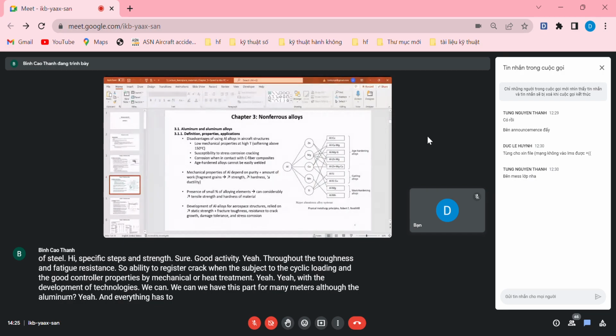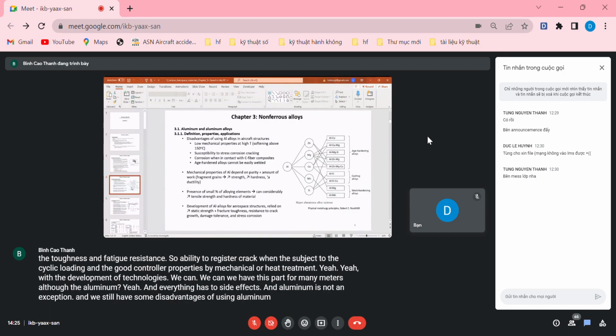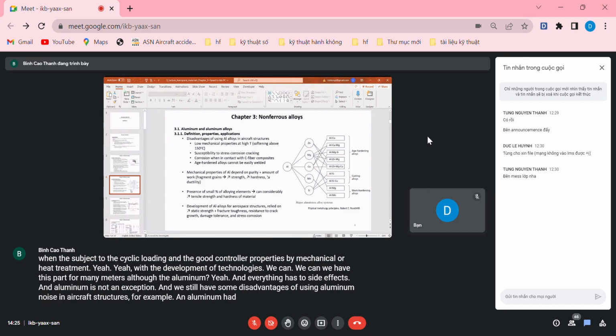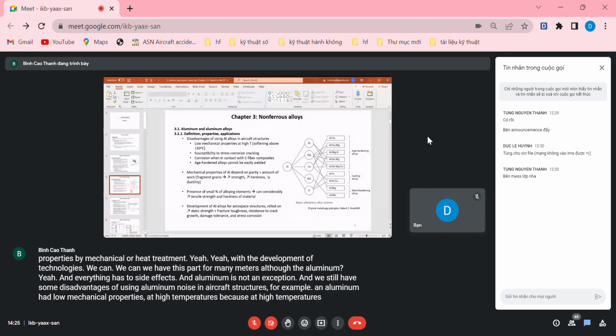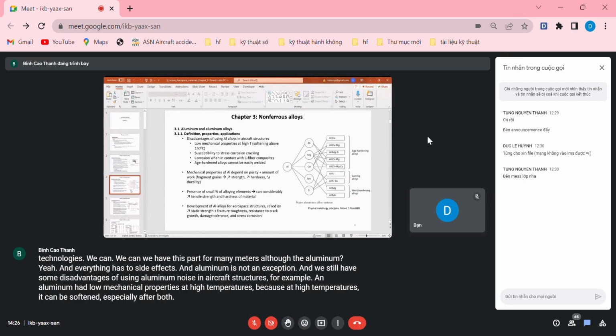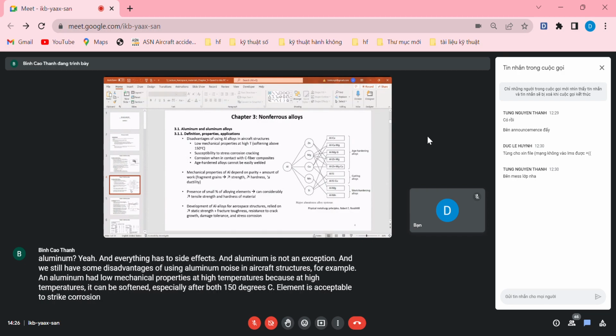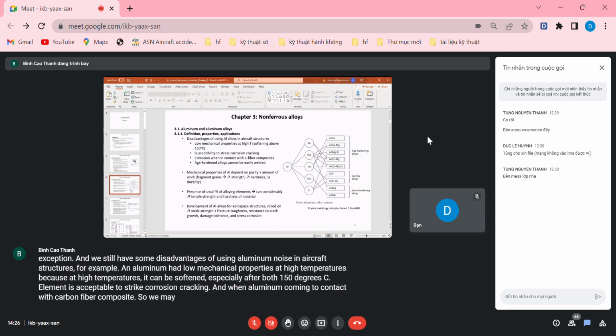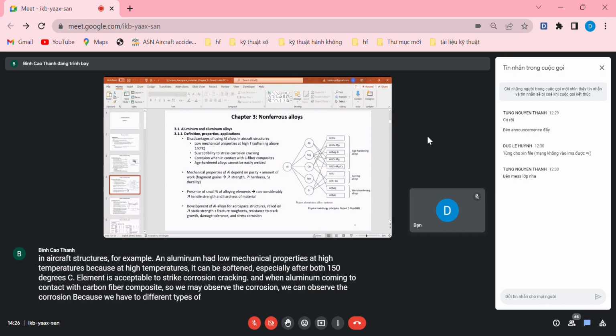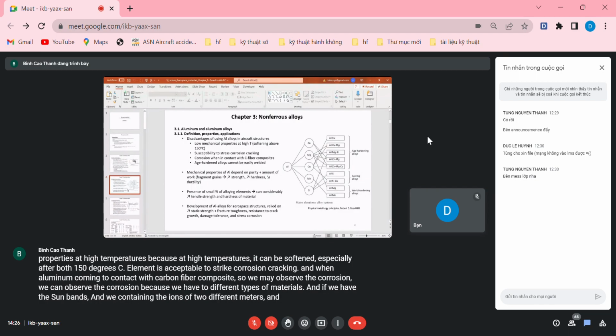Everything has two sides, and aluminum is not an exception. We still have some disadvantages of using aluminum alloys in aircraft structures. For example, aluminum has low mechanical properties at high temperatures, because it can be softened, especially above 150 degrees C. Aluminum is susceptible to stress corrosion cracking. And when aluminum comes into contact with carbon fiber composite, we may observe corrosion, because we have two different types of materials, and if there are solvents containing the ions of two different metals, it can promote the corrosion process.